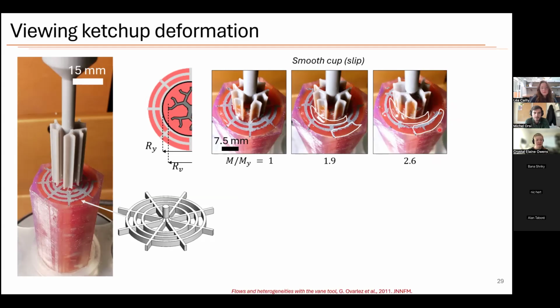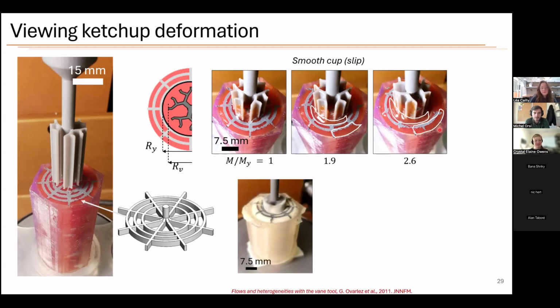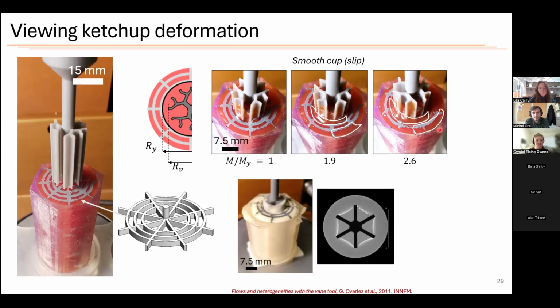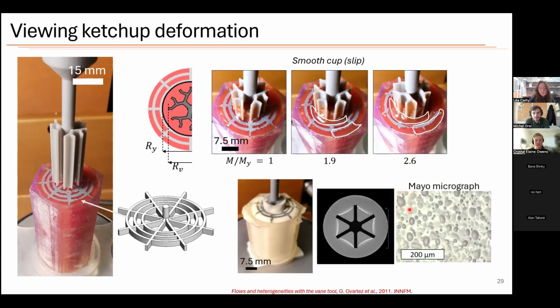And this is in contrast to other measurements we did of mayonnaise. It turns out ketchup is America's 3rd most popular condiment, and mayonnaise is 1st. It's about twice as popular. But mayonnaise is actually extremely difficult to measure, not because of thixotropy or anything, but because it shear bands. And this has been studied before in careful MRI studies of emulsion-like structures. The microstructure of mayonnaise is that it has oil and water emulsions, and with these sorts of materials, it's very easy for them to form depletion zones within the material.